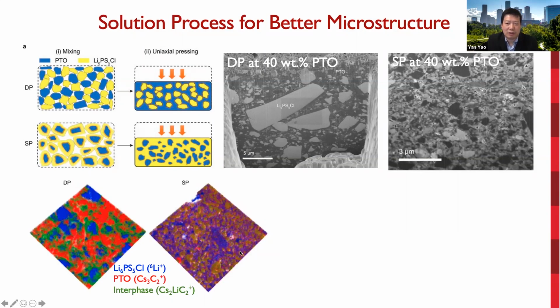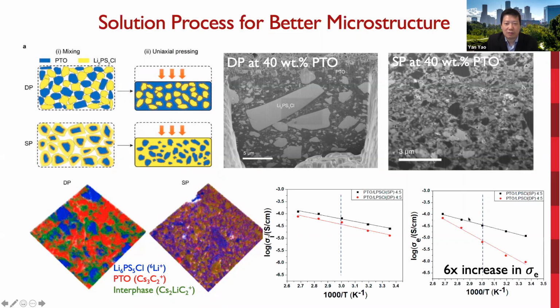The images not only confirm more uniform spatial distribution of PTO in the solution process compared to those in the dry process, but also provide molecular information of the interface. So we find the green one related to the PTO is partially reduced to form lithium-x PTO, and also the electrolyte is partially oxidized to polyphosphate. So the solution process also results in a slight increase in ionic connectivity and a 6 times increase in electronic connectivity, leading to a balanced transport in the solution process sample.